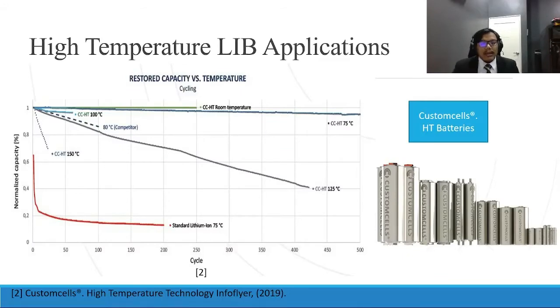Moving on, and we have custom cells batteries. Custom Cell is a company that made custom battery especially for high temperature usage. So the picture on the right is the battery that they produce, and on the left there is a graph of restore capacity versus temperature. As you can see on the blue line, at 75 degrees Celsius constant current high temperature battery usage, the battery performs 500 cycles with more than 0.8 normalized capacity, while the standard lithium-ion nowadays only performs 200 cycles with 0.2 normalized capacity left, and the difference is quite big for a battery made by custom cell and the standard lithium-ion battery.